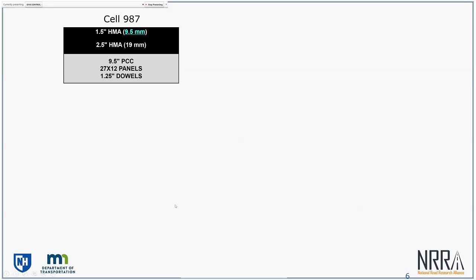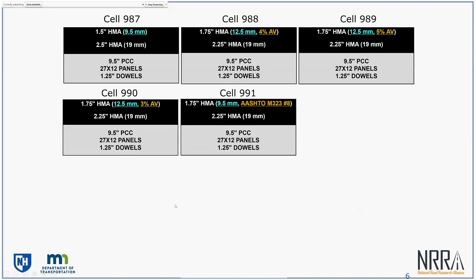So the first cell you see here is what I call my baseline overlay type of cell: 2.5 inches of 19 millimeter mix right on concrete, and then 1.5 inches of wear course, which is 9.5 millimeters, so 4-inch total overlay thickness, and that's what we would use more as a baseline or a control overlay. And then to compare to that, you see 4 more cells here. And what's really changing between these cells is, if you see the course that's going right on top of concrete, they are all 2.25 inch. That's not really changing, but on surface, you can see these 4 different mixes, where now we have our traditional 1/2-inch mix with 4% air void design air void level. That's your standard Superpave mix.